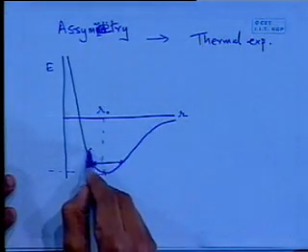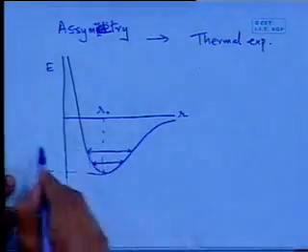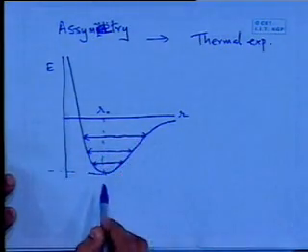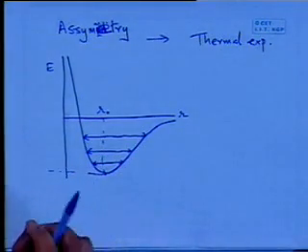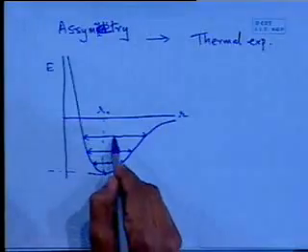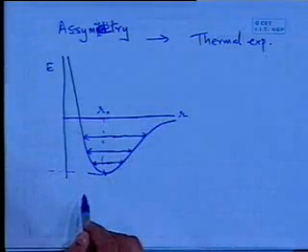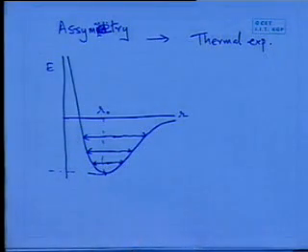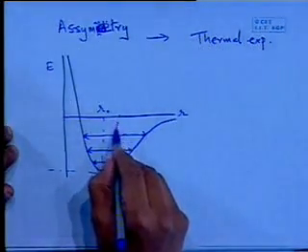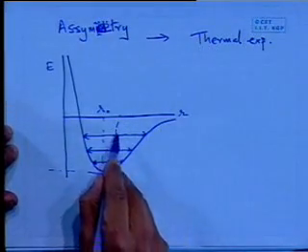And we do the same thing, higher energy, higher temperature, it gets more energy, and it vibrates between these 2 points, and so on. Now what you notice is here, that while it was sitting here, it was sitting at an average distance R naught from each other. But as the temperature has gone up, more energy is supplied to the system, the midpoint of these is gradually shifted due to the asymmetry of the curve. In other words, the average separation of these atoms, as they have risen in temperature or increased in energy, is now farther apart than the R naught at which they sat at equilibrium. And therefore, when we look at it, we say the material is expanding.